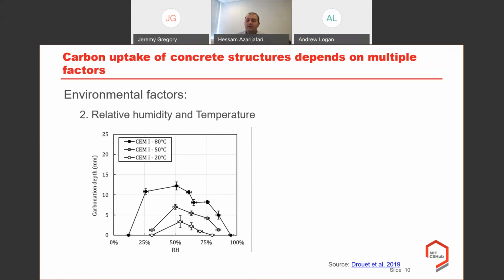When relative humidity is too low, there is insufficient water in the micropores within the cement paste. And there is low possibility of the formation of carbonic acid in this case. Therefore, we observe near to zero carbonation depth in a very low relative humidity. But on the other hand, when the pores are full of water, let's say in 100% or close to 100% relative humidity, the diffusion of CO2 into the paste is very slow.